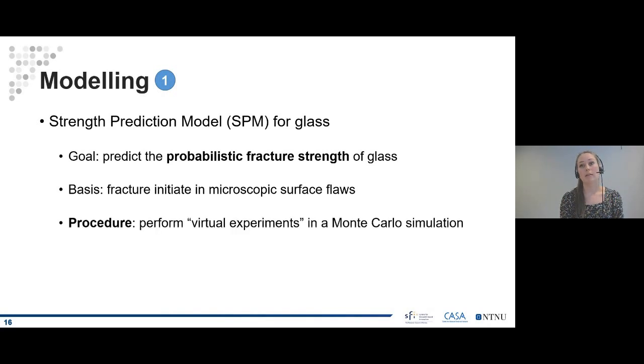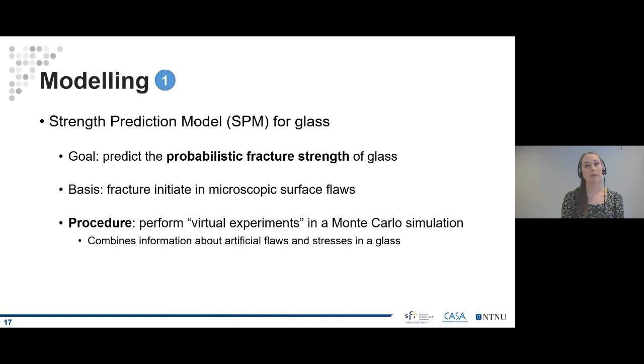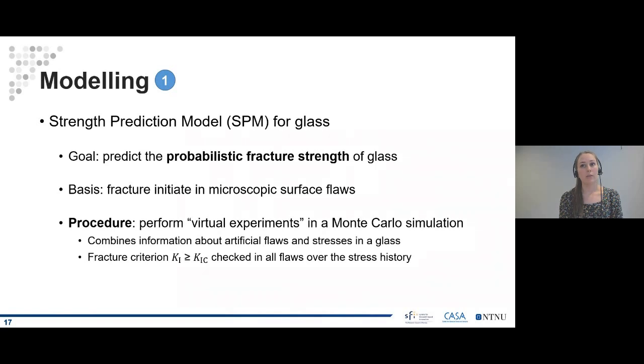What we do in this model is perform virtual experiments in a Monte Carlo simulation. So we combine information about artificial surface flaws and stresses in a glass. The stresses we can get from a finite element simulation or an analytical solution. Then we check the fracture criterion that I presented earlier in all of the different flaws over the entire stress history. And then we output the relevant fracture information if we get fracture in one of the virtual experiments. And we have to do many virtual experiments to get a proper failure distribution.